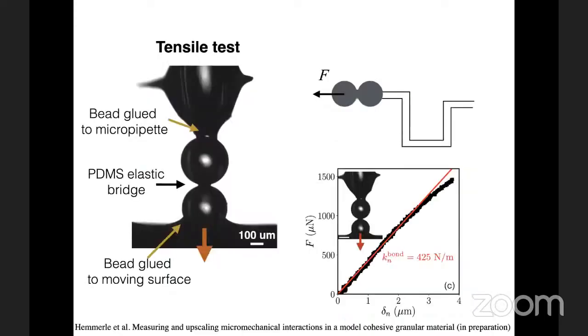And we made some experimental tests with a micromechanical testing rig. This consists of taking one of our materials apart until we have only a very small fraction of it, which consists of two particles held together by a bridge. Gluing that particle assembly to a very tiny micropipette, and then under a microscope, stretching that pipette until we can see the deformation. It's a micromechanical testing rig, basically.